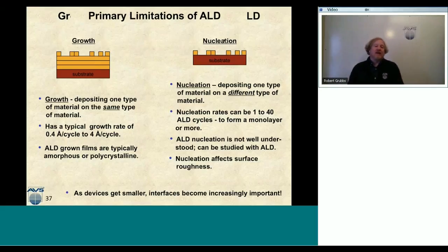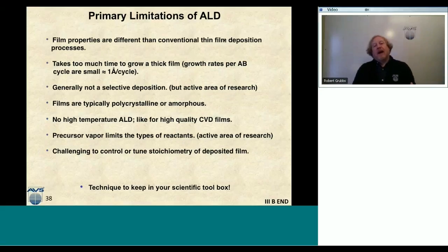So some of the limitations of ALD, I have them listed here. The properties of the ALD grown films are different than our CVD analogs or our sputtering analogs. So this is really important. And it just has to do with how the process is run. As we know, CVD can be very, very hot. We have deposition, we have reactions in the near surface region. But in ALD, we bring them in sequentially. We don't have a near surface region reaction. We can never get an ALD chemistry too hot, or else we'll see decomposition. So the ALD films have different properties than the conventional films. That's really important to take into consideration, especially if you've been relying on a film for a specific process and you want to move to that equivalent ALD process, that ALD film might not have the same properties that you're looking for.